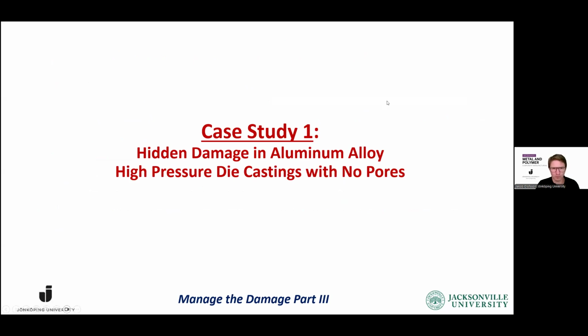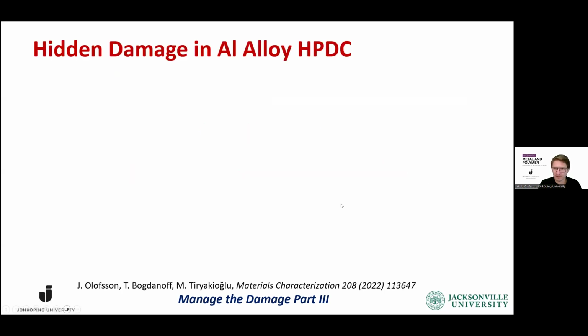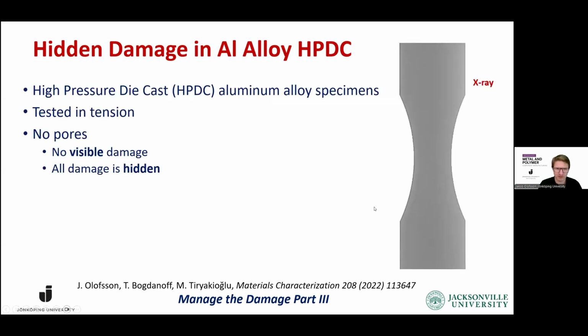Yep. So then we will take a look at this case study where we are looking at this hidden damage in an aluminium alloy. So what we will be looking at is a high pressure die cast material where we have now done X-ray to confirm that there are no visible pores in this material. So if you go to the next slide and start moving forward, we can see the shape of the specimen. It's a high pressure die cast aluminium alloy specimen, as I said. You see the shape is not as we usually use in tensile testing. It's not a pure dog bone specimen.